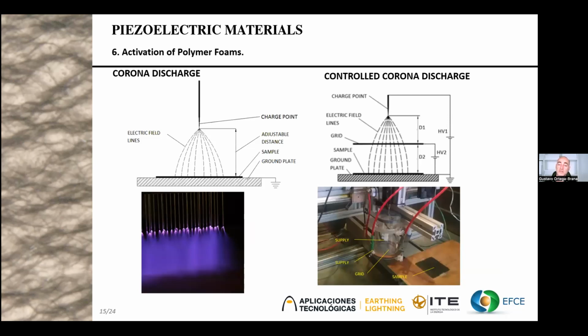In order to trigger the internal discharges in the voids of the polymer, a high external electric field has to be applied to the samples, as we said. On the left picture, we can see the corona discharge arrangement with a tip and a ground plate, and that is the color of the corona discharge and the cone that it produces on the plate. On the right, we can see the triode corona discharge arrangement, for better control of the surface charge. In this case, the surface of the sample will be charged at the same voltage as the grid between the tip and the sample. That is the setup that we use for our measurements.